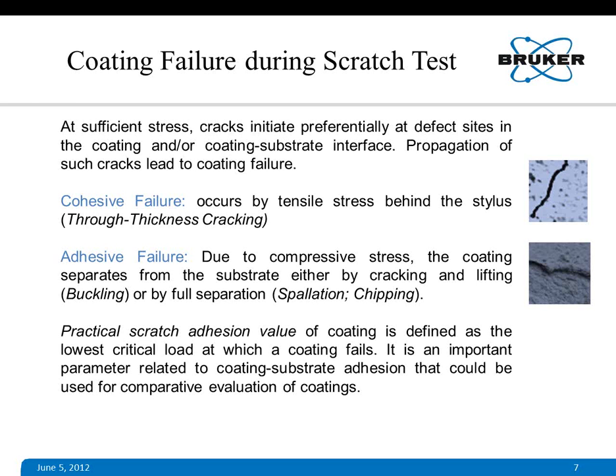Adhesive failure actually happens due to compressive stress, which is present ahead of the stylus tip, whereas cohesive failure happens with tensile stress. Tensile stress is the major driving force for cohesive failure. The practical scratch adhesion value of a coating is defined as the lowest critical load at which a coating fails. It is an important parameter related to coating substrate adhesion that could be used for comparative evaluation of coatings.